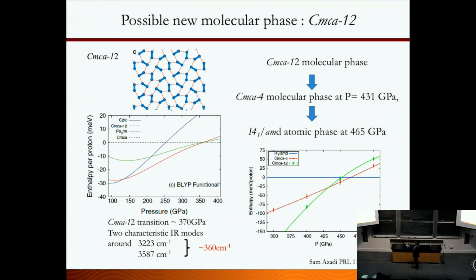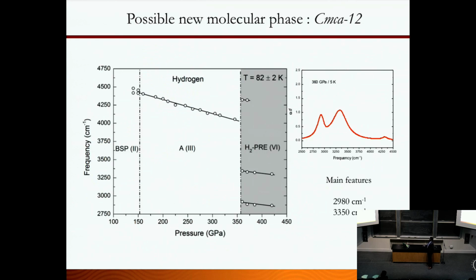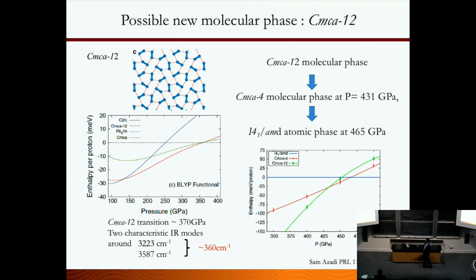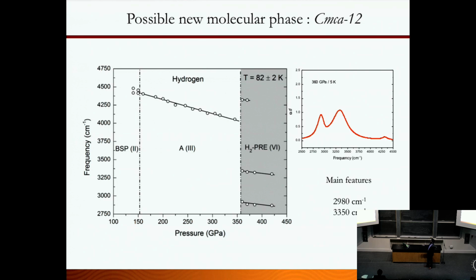You can have this new phase called CMCA12, and it has two main characteristics via IR vibron, 3223 and 3587. But I just want you to point it out and look into the difference between these two peaks. It's around 360 inverse centimeters. So if you go to my new phase right here, the difference between these two peaks is 370. But these two peaks are much softer than this one, right? This is around 32 and 35. This is around 29 and 33. This is a little bit different, softer than what the theory predicted.